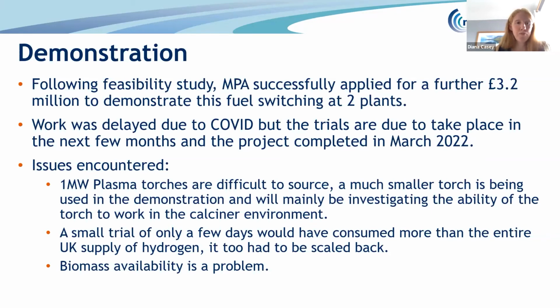So far, the preparatory work for those physical demonstrations has raised quite a few issues which we weren't necessarily expecting. First of all, we were looking at using 1 megawatt plasma torches. They are really difficult to source and they're extremely expensive. They tend to be much smaller powered units. So what we're having to do for the demonstration is use a much smaller torch. And because it's not going to be inputting the kind of heat demand that we were hoping for, we're really using it now to investigate the ability of the torch to work in that kind of calciner environment, if it can withstand the dusty conditions without the anodes and the cathodes deteriorating so quickly that we have to continually replace it.